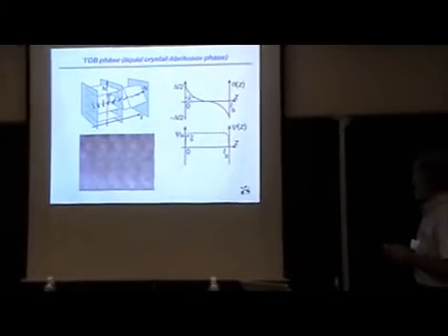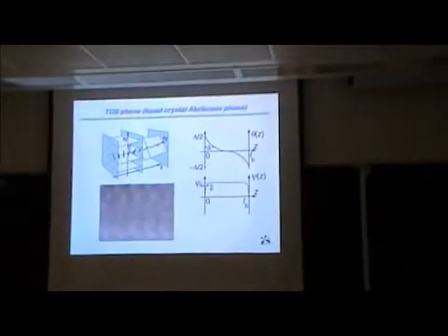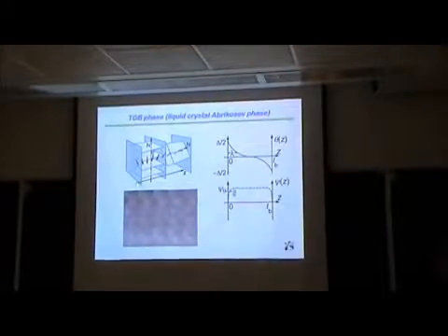So what happens is that the layering, this happens where the layering is in some sense weak. So you get slabs of smectic layers in which you can have twist, and then you make the twist continuous at the expense of jumping the orientation of the layers. So these blue sheets here are grain boundaries in the orientation of smectic layering that enables twist. So this is a TGB phase.